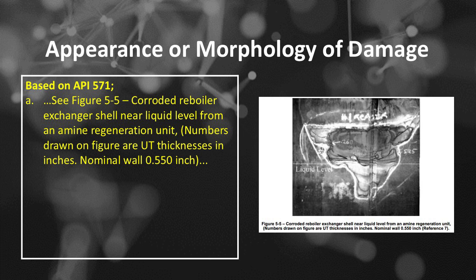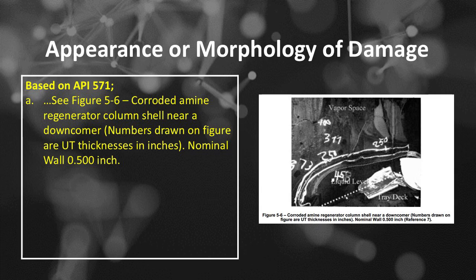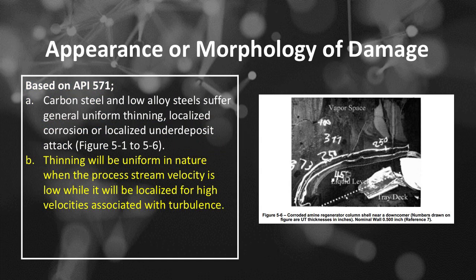Nominal wall 0.550 inch. See Figure 5.6, corroded amine regenerator column shell near a downcomer. Numbers drawn on figure are UT thicknesses in inches. Nominal wall 0.500 inch. B: Thinning will be uniform in nature when the process stream velocity is low, while it will be localized for high velocities associated with turbulence.